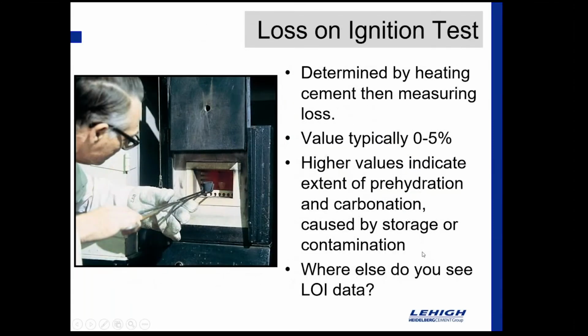So if we continue down the left side of our mill test, we find the loss on ignition test, and that's determined by heating cement, then measuring the loss. So you just take a platinum crucible and put in a 1.00 gram sample of cement, and you heat that at 900 C. After a specified time, you pull that out, cool it, weigh it again, and you're looking at that loss in the overall weight, what you started with versus what you end with after heating. Typically you see that value somewhere between 0 to 5%.